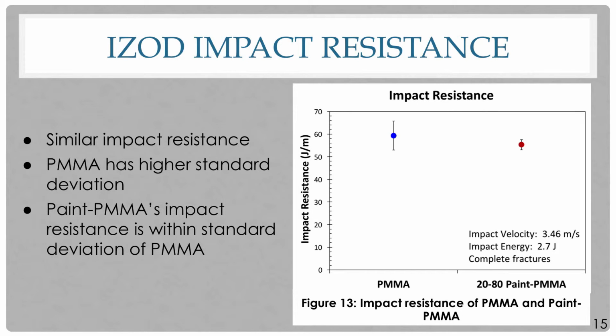The IZOD impact test was performed to measure impact resistance, which is the energy absorbed upon impact. If we take a look at figure 13, the blue dot representing the PMMA is slightly higher than that of the paint PMMA. However, something interesting that we want you to take note of is that the impact resistance of the paint PMMA actually falls within the standard deviation of the PMMA.